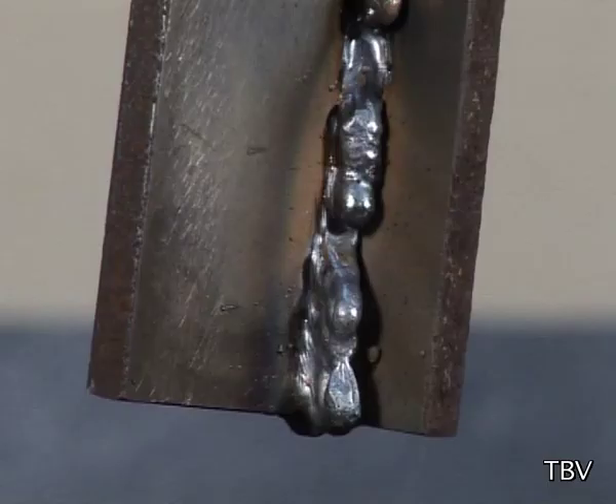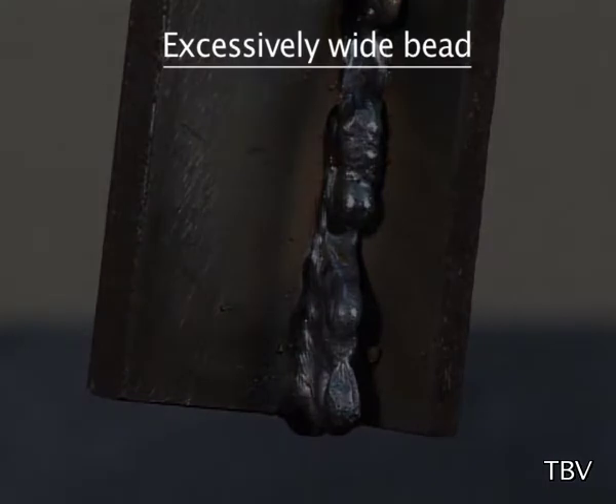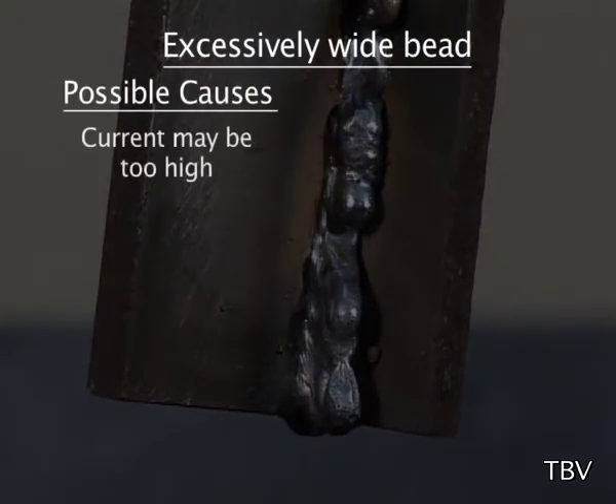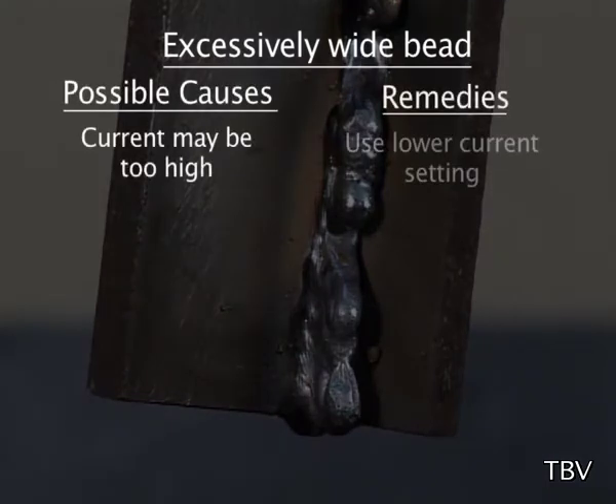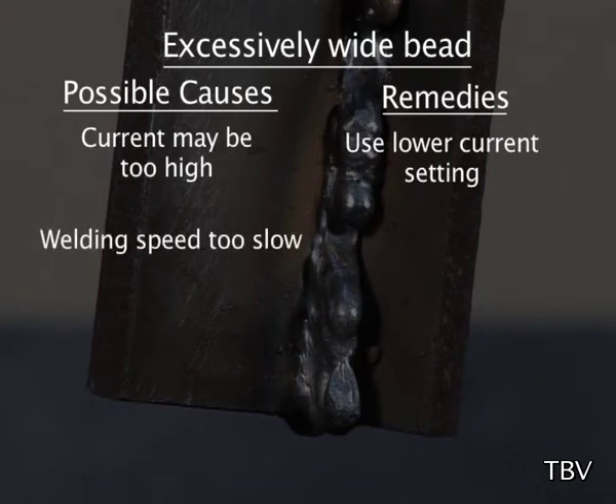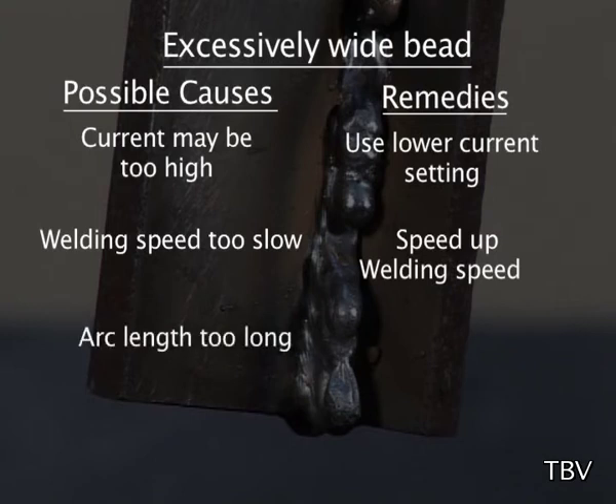Defect: excessively wide bead. Current too high. Use lower current setting. Welding speed too slow. Speed up welding speed. Arc length too long. Shorten arc length.